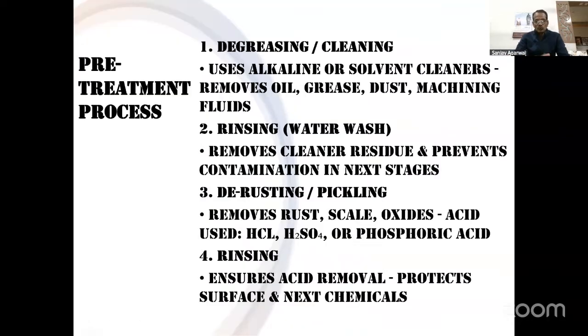Then we move to the cleaning process, pre-treatment. When the manufactured part is welded, it has to go for powder coating, painting, or a plating process. Before plating or powder coating, we have to clean the part very properly and prepare the surface for adhesion of the paint, and it should be corrosion resistant. So it is an 8-tank or 10-tank process. The process is as follows.